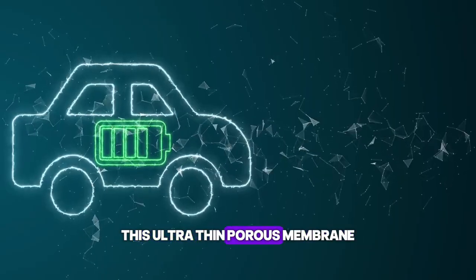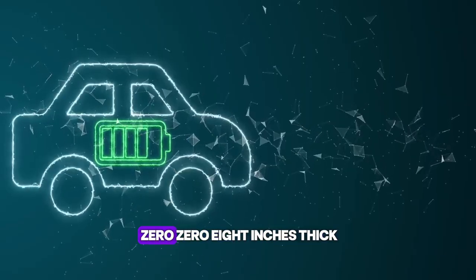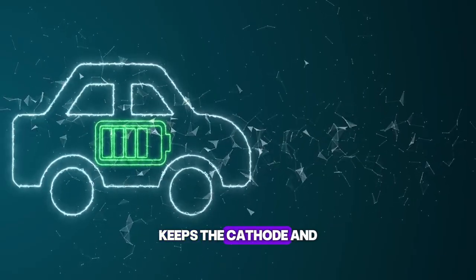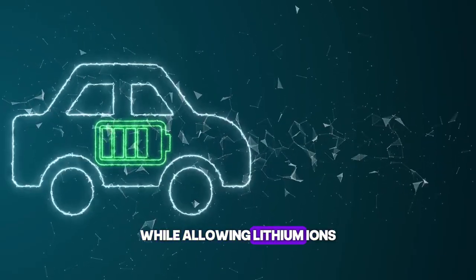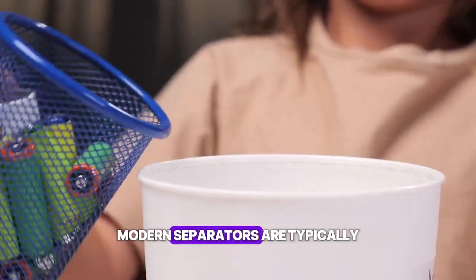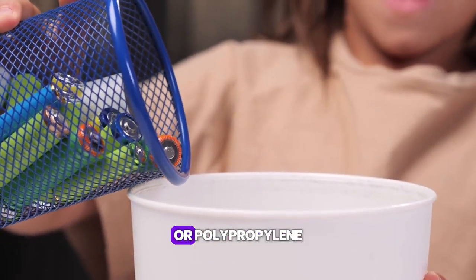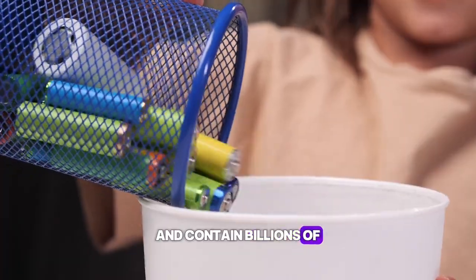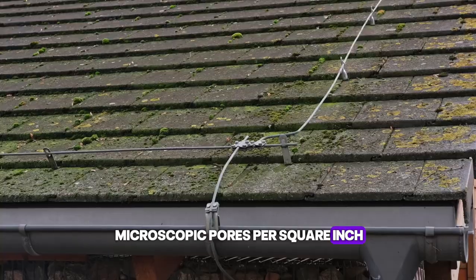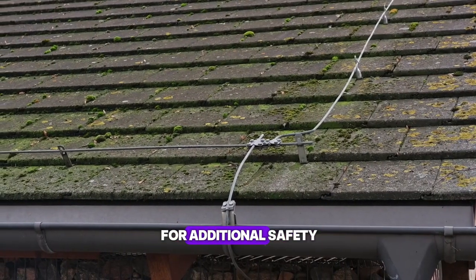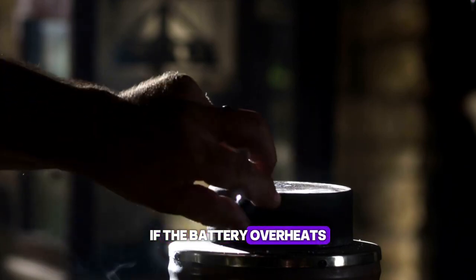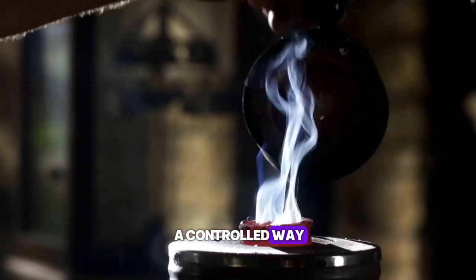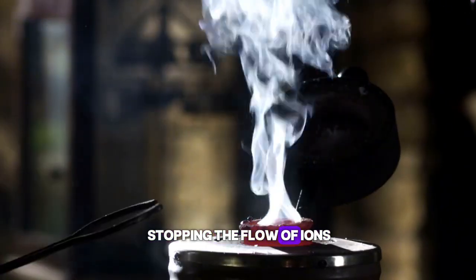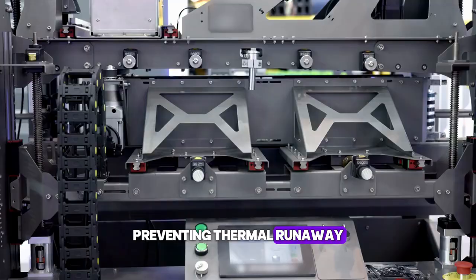This ultra-thin porous membrane, often less than 0.008 inches thick, keeps the cathode and anode from touching while allowing lithium ions to pass through. Modern separators are typically made from polyethylene or polypropylene and contain billions of microscopic pores per square inch. Many incorporate ceramic coatings for additional safety. If the battery overheats, the separator melts in a controlled way, closing the pores and stopping the flow of ions, preventing thermal runaway. The assembly process requires extraordinary precision.